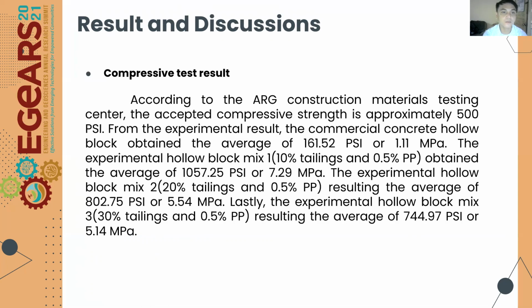Next is the compressive test result. According to ARG Construction Material Testing Center, the accepted compressive strength is approximately 500 psi. From the experimental results, the commercial concrete hollow blocks obtained the average of 161.52 psi or 1.11 MPa.